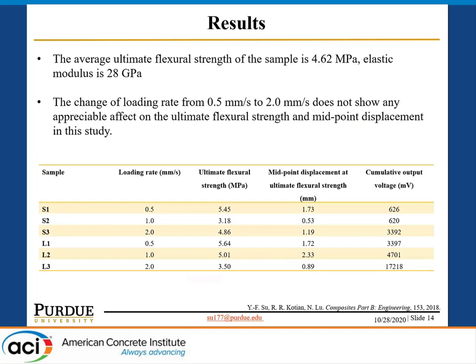So here's the mechanical test result. The average ultimate flexural strength of the sample is around 4.6 megapascal, and the elastic modulus is 28 gigapascal. The change of the loading rate from 0.5 to 2 millimeter per second does not show much effect on the flexural properties.